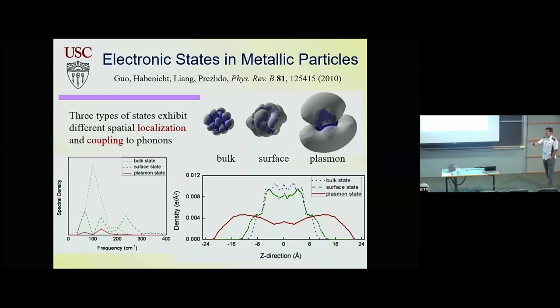So the barrier that Sasha was describing actually is not such a bad barrier, because your state is delocalized a lot into the barrier. And because it's localized away from the core, electron vibrational coupling is very weak. So this red peak is very low. So the relaxation, loss of energy to heat, is also pretty slow.